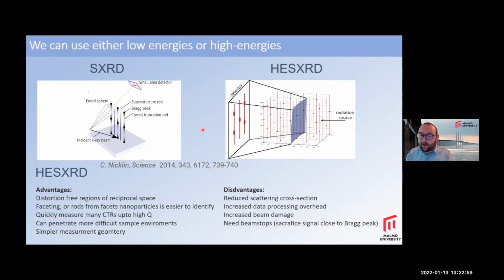Some of the problems, though, are the sensitivity is worse. You have a reduced scattering cross section, and I think some materials are very difficult to measure with high energies. And the data processing, because you typically use large area detectors at high energies, is dramatically increased. And in some sample environments, beam damage can be more of an issue. And then the current dynamic range of detectors is fairly limited. So if you want to measure the weak crystal truncation rod signal between the Bragg spots, you need to put beam stops in the way of the Bragg spots, because otherwise they'll just saturate your signal.